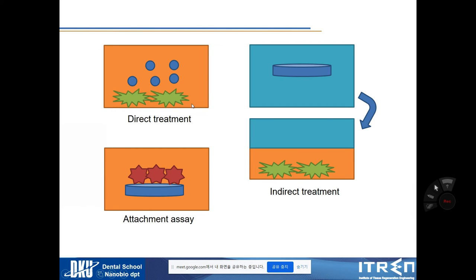After getting these nanoparticles, there are several ways to investigate the biofunctionality. The first is called direct treatment, which means I directly co-culture the cells and nanoparticles together. The second is when I make a disc specimen as a cement and seed our pulp stem cells on this disc. This is called an attachment assay. And like making coffee from coffee powder, I extract conditioned media from this specimen or nanoparticle, and then use the extract to culture the pulp stem cells. This is called indirect treatment. So over three different conditions, I evaluate my nanoparticle's biofunctionality.